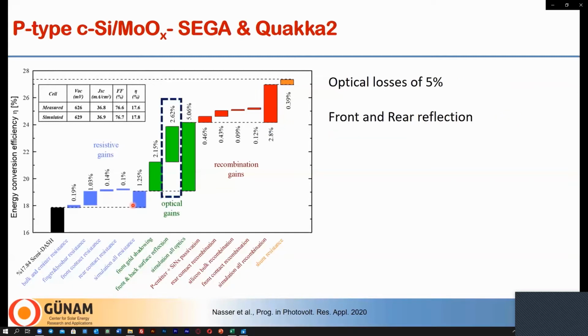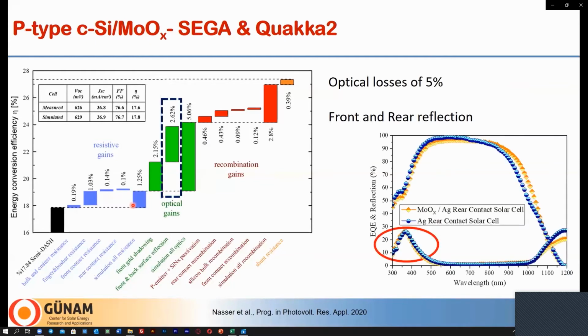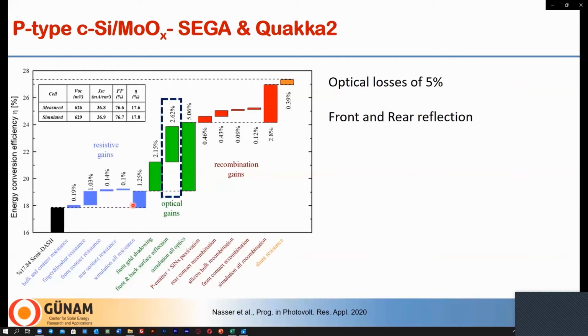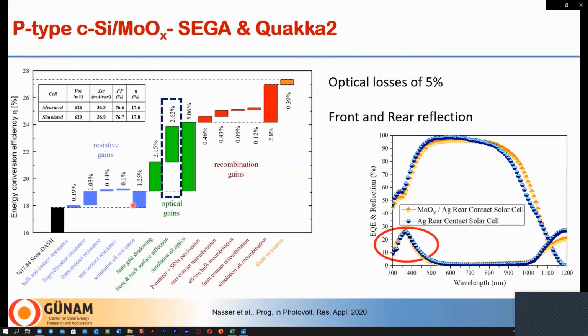Most essential here is to avoid optical losses with potential gain of above 5%. And we found that the front and rear reflection is the most dominating individual loss mechanism here with more than 2.6%. So if we look at the total reflection, we see that it is high at shorter wavelength with more than 25%. It's known that this wavelength range is related to front side reflectivity. So it's related to front side texturing and silicon nitride.